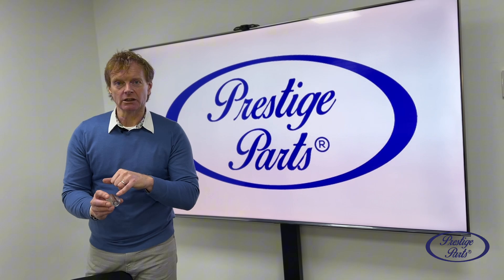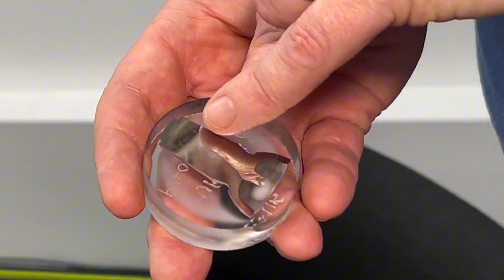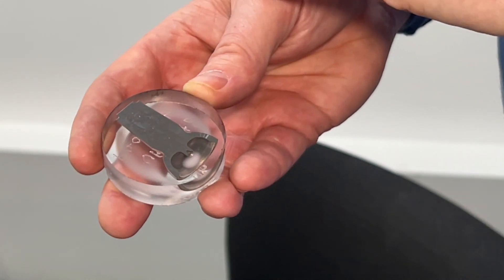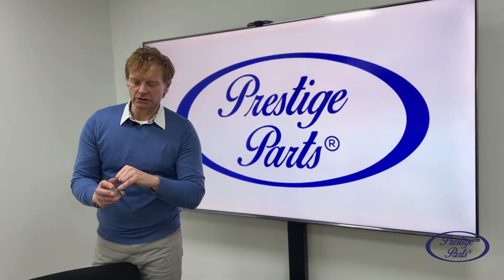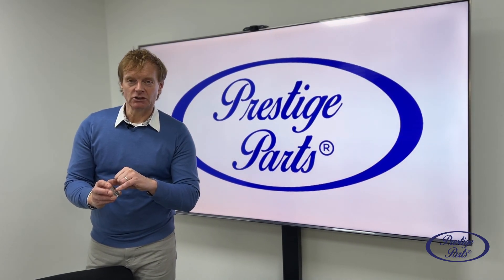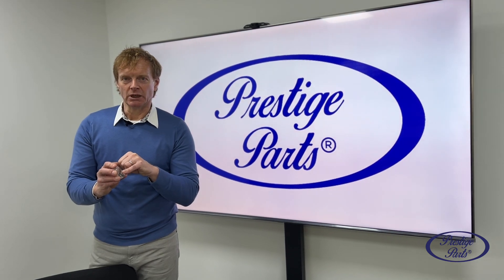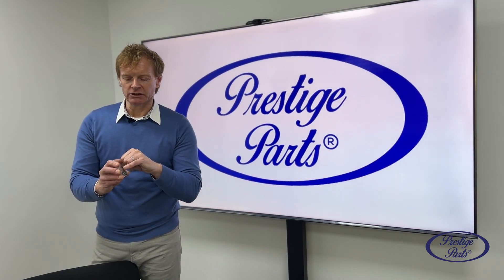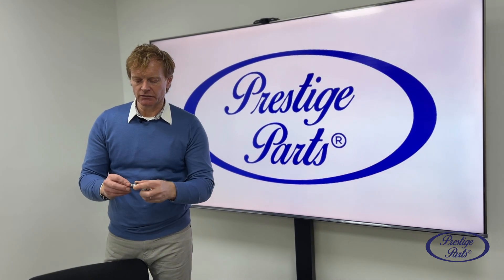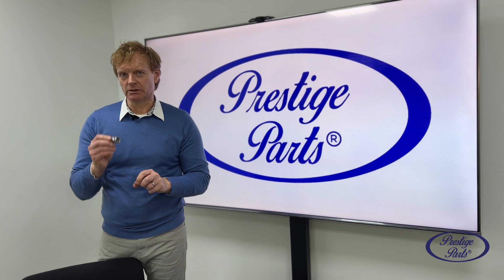This is a slug — and if you get really close you can see three little dots. That is where the hardness testing has taken place, so we get different hardnesses at each of those three places. We know that this isn't still soft on the inside but hard on the outside just here. So when you're making this, you mask this area off, heat treat this part, make it hard, but the rest of it remains ductile. Absolutely critical.